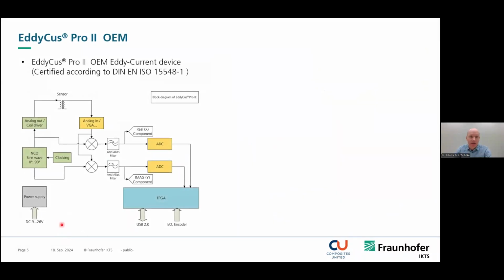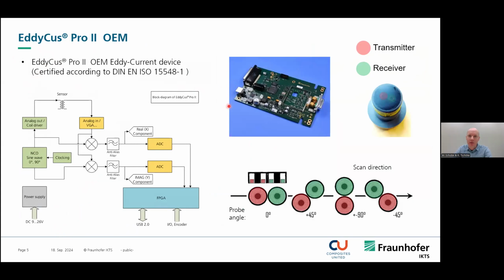To analyze these carbon fiber materials, we have our own device, the Eddicus Pro 2 OEM. This is a typical eddy current system, but with a unique feature, the high frequencies. We can measure with frequencies up to 100 megahertz. Because of the low conductivity of the carbon fiber material, we need these high frequencies to get a sufficient amount of energy into the material and to get a significant response out of the material that we can measure.